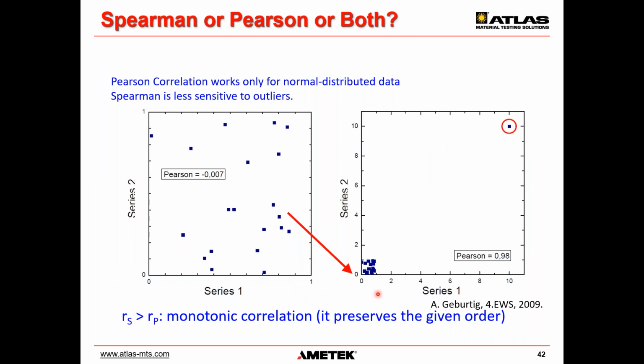What's better to use, Spearman or Pearson or both? As mentioned in the beginning, Pearson works for normally distributed data. As soon as you have outliers, it's completely screwing up everything, while Spearman is not so sensitive to outliers. And typically, the Spearman correlation coefficient is bigger compared to the Pearson correlation coefficient. If that's not the case, then you don't have a monotonic correlation anymore. It does not preserve the given order anymore.